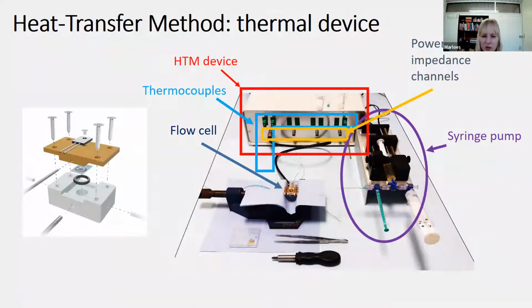What we have at the moment is a little device, all made in red, which is a homemade thermal device that can control the temperature, but it also measures the temperature. It allows you to have a certain temperature within a heat sink, a copper layer, and then we measure the temperature just below the sensor itself. This temperature gradient is related to your thermal resistance.